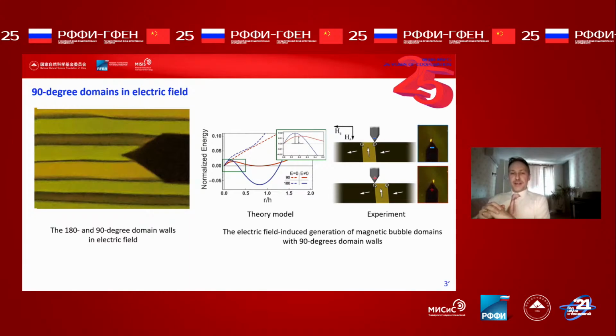Here we can see, on the left, the magneto-optical image of the domain structure, and the black area is a tip electrode, an electrode from the atomic force microscopy tip in contact mode.